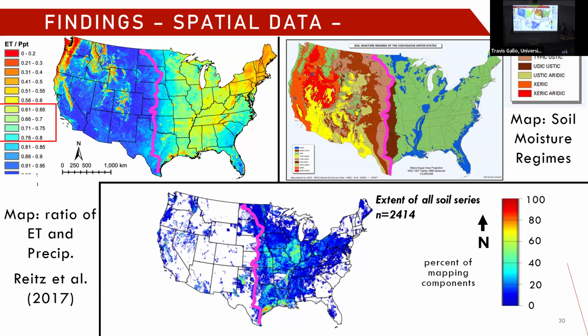The geographic boundary supports what we think about manganese redoximorphic features, that they need the moisture to become reduced enough in the soil to then become reoxidized. So on the right-hand side of this line, you have soils that are humid to semi-arid, and on the left-hand side of that line, you have arid soils where there's not enough moisture for the manganese to reduce and then reconcentrate. And so that may be the main explanation as to why there's not that many manganese redox features described in OSDs to the left of that line.